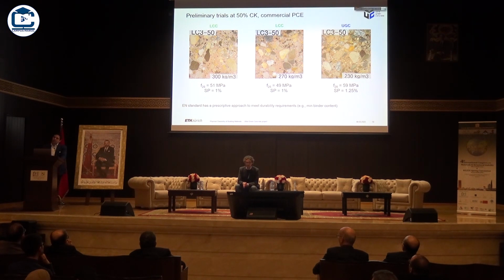The problem with all of these technologies is that the EN standard for concrete has a prescriptive approach to meet the durability requirements, which is basically a deemed-to-satisfy idea. There is a certain water to cement ratio, there is a certain minimum binder content that someone, based on experience, established is required to meet a certain criterion of durability performance.